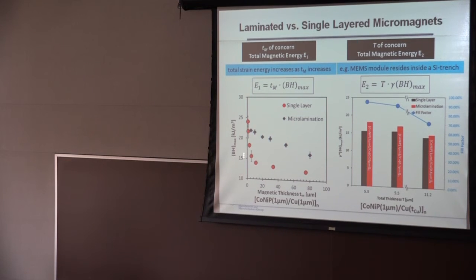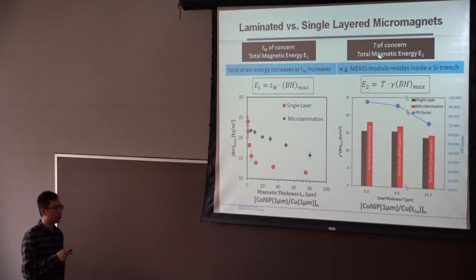Here we show a plot of BH max versus the magnetic thickness. The strategy in this case is to pad the individual layers thicker, so you can both retain the good properties of the thin film and reduce the average stress to improve mechanical stability. Here we chose a relatively thicker copper film. As you can see, the energy density was relatively well kept in the multilayer structure compared to the single layer, which plummets in this 1 to 5 micron region. Because of this, we were able to have a relatively larger total magnetic energy in the microlaminate case compared to the single layer.